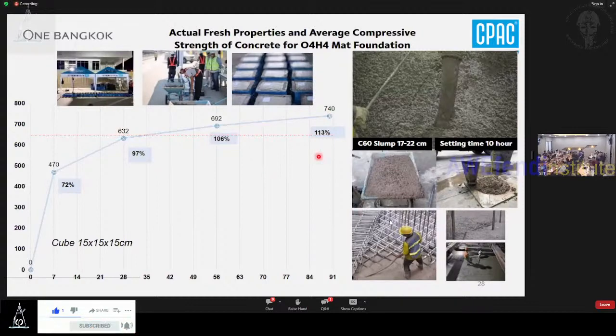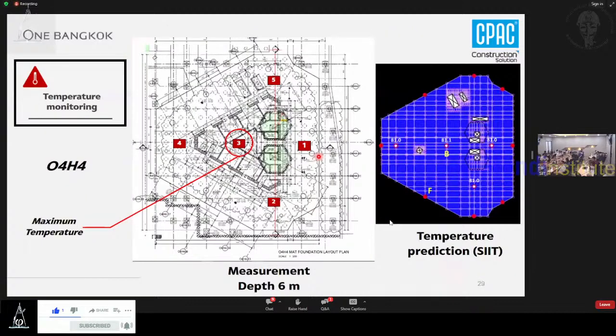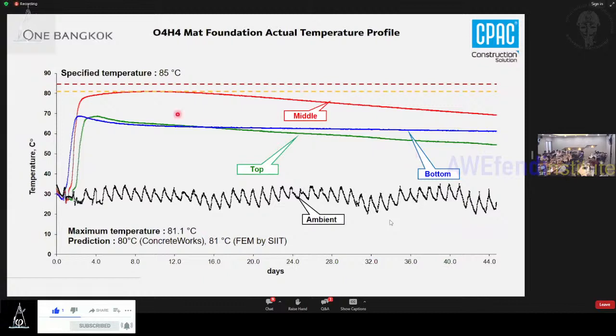So it's quite happy for our issue. And after that, we put thermocouples to monitor the temperature at each point. And you can see here, we get the number around 81.1. We compare. You can see here the specified maximum temperature, and the red line is the middle temperature that we measured from the real structure. And you can see the maximum is around 81.1, and we predicted around 81 from SIIT.